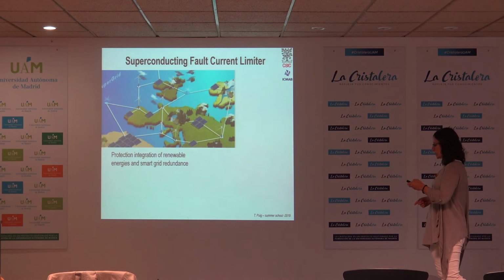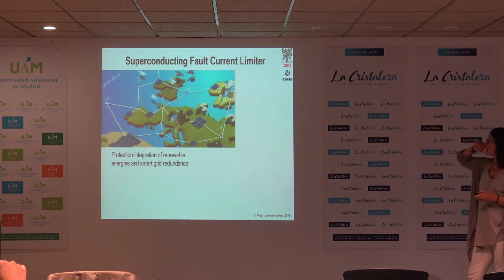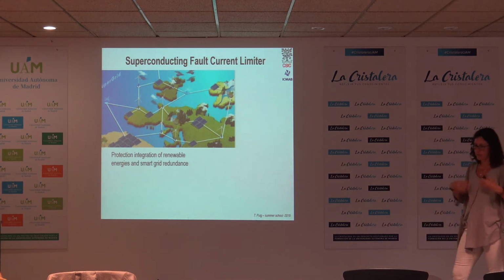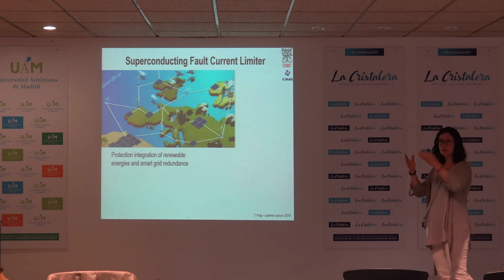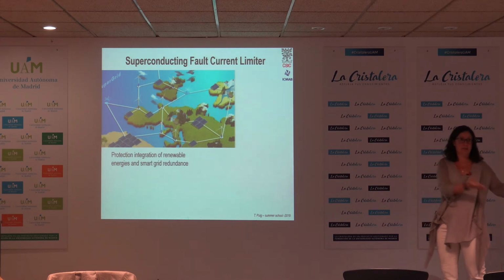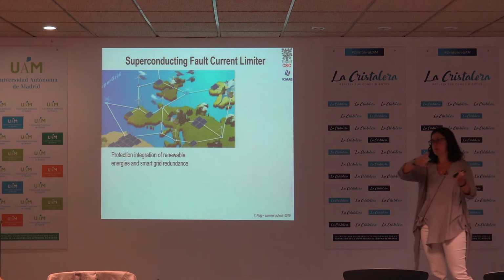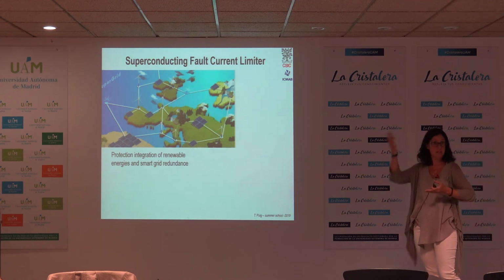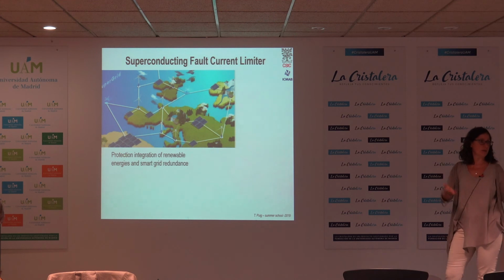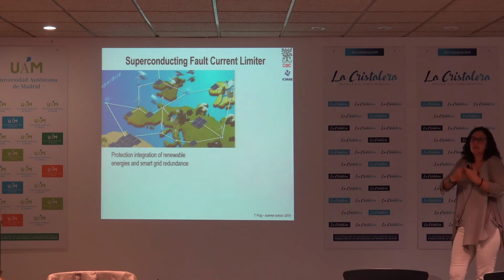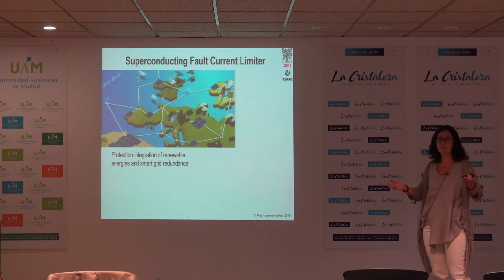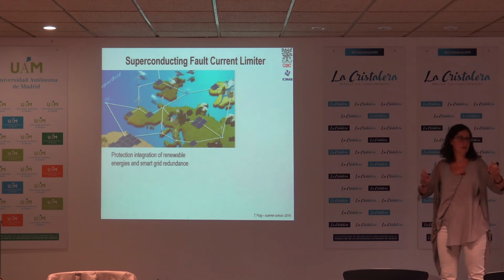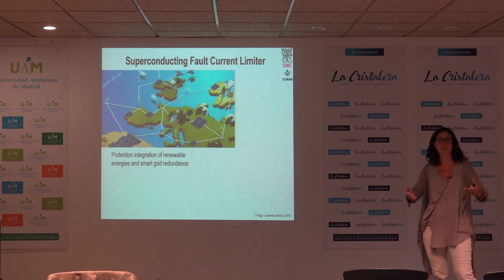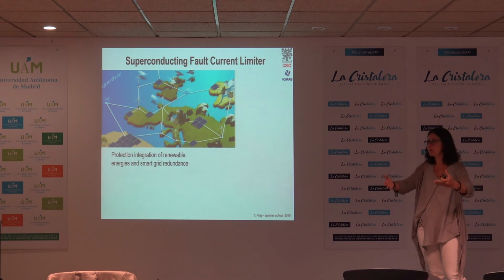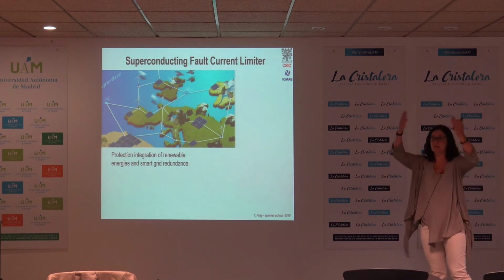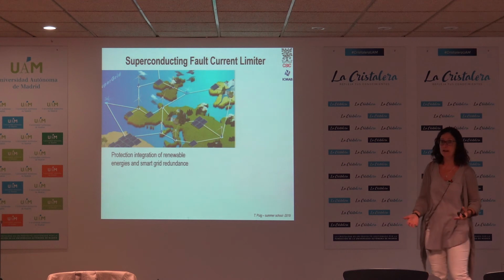A fault current limiter is interesting. It is a system which is able to benefit from the superconducting transition. A superconductor in the superconducting state has no resistance. When it goes to the normal state, it has a resistance, and therefore we can put a superconductor in a network, and if it's in the superconducting state we don't see anything. But if there is a current fault, then the critical current will be exceeded, and therefore we will put an impedance into the network, increasing the resistance and therefore decreasing the current of the network.